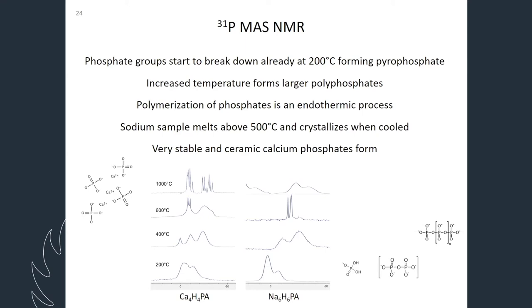Sodium is less stable, so here we have nothing left of our sodium phytate. Everything has polymerized into pyrophosphate and polyphosphates. If we increase to 600 degrees, we can see that we get some more crystalline, we get more narrow peaks. It means that the sample has started to crystallize.